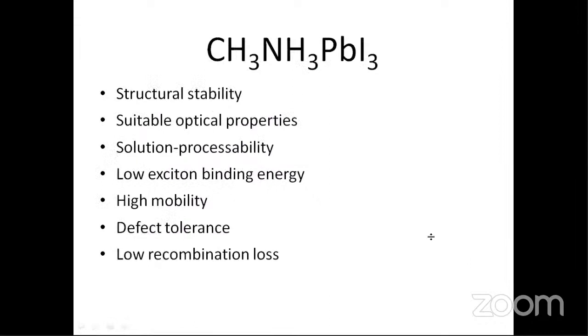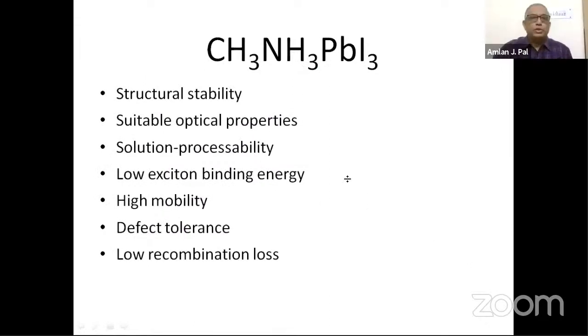Yeah, it's perfect. Okay, so I was talking of different properties of methyl ammonium lead iodide: why it is structurally stable, why it has suitable optical properties, and why it is solution processable, because for most large area devices we need solution processability, otherwise we cannot go for large area devices. And then low exciton binding energy, that is, the charge separation should occur very quickly without much effort of energy. So I need to separate the carriers. So that is the low binding energy. And also I need to extract the carriers very quickly, so I need high mobility.